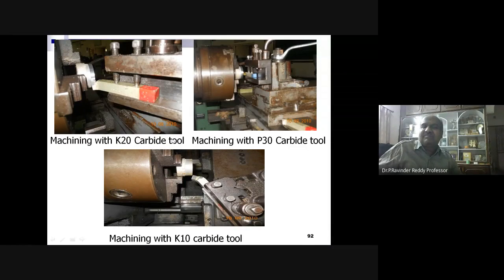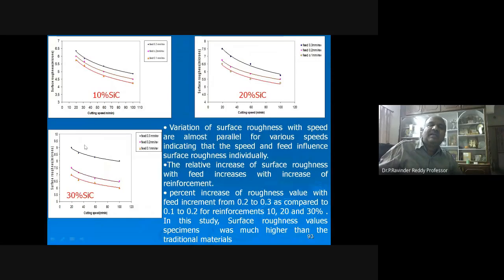You can see here the work and the tool. The machining with the K20 carbide tool, you can see the tool and work inserted. Again, the tool you can see with K10. So 10%, 20%, 30% with the different cutting speeds and feed rates, we can observe the surface roughness is decreasing while cutting speed is increased. And you can also observe that at 30%, it is going to be better.